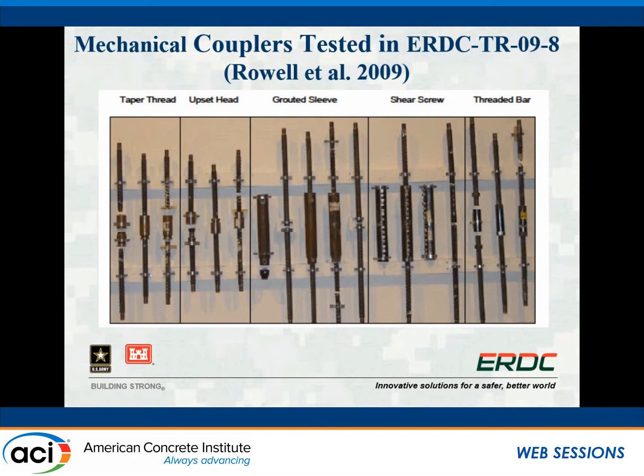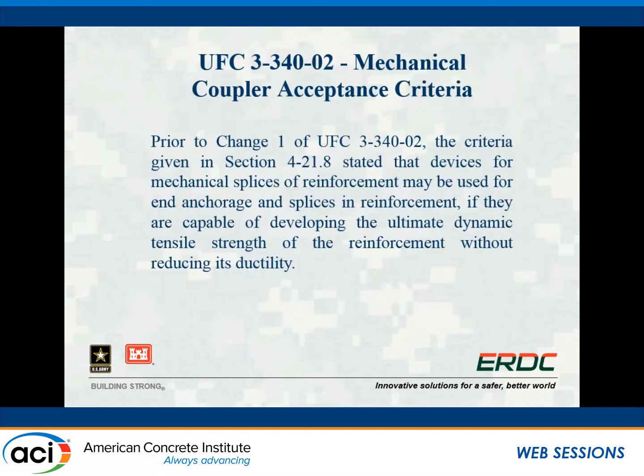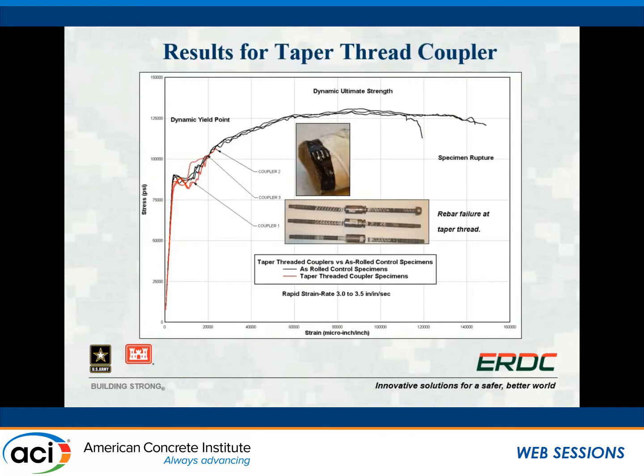If we look at that guidance prior to Change 1 made in UFC, again, it requires that if we're going to use mechanical splices of reinforcement, they have to develop basically the same dynamic tensile strength and the same ductility. We're going to step through a lot of data and look at how that's very difficult and basically impossible to achieve with most of these. Even in a perfect system, they still introduce a defect or discontinuity that makes these systems prone to reducing mechanical properties somewhat.